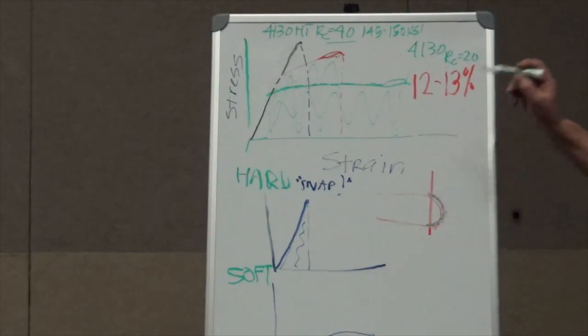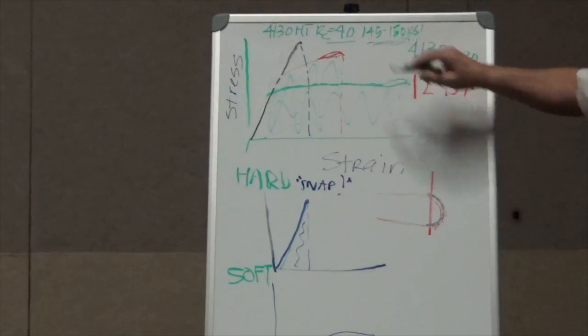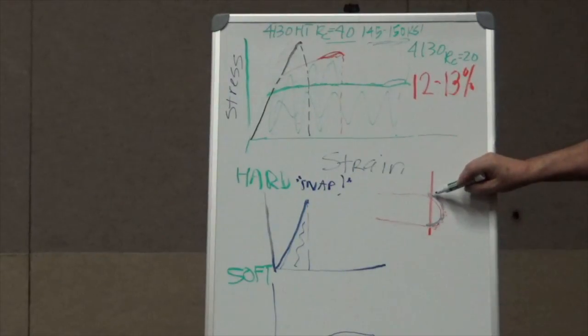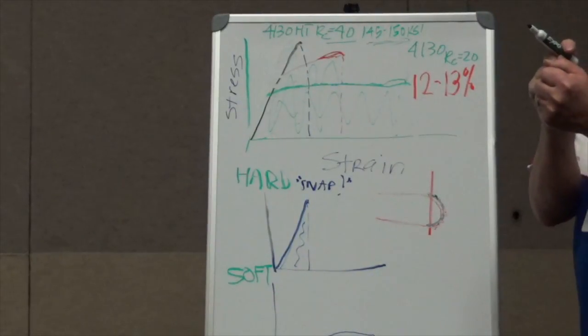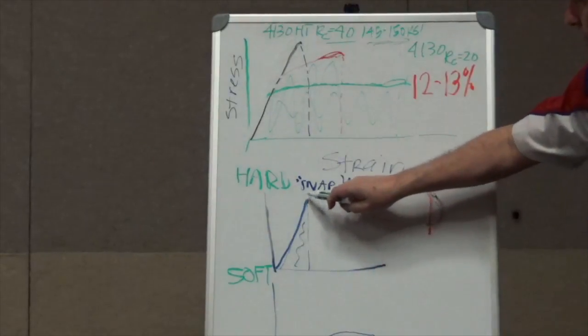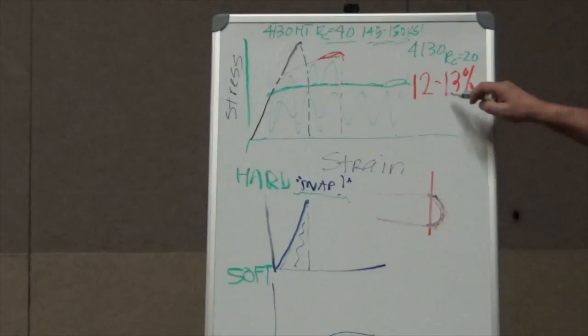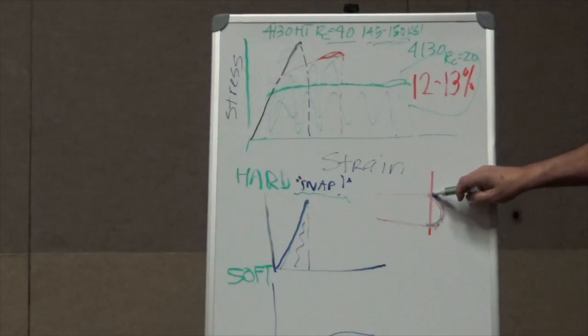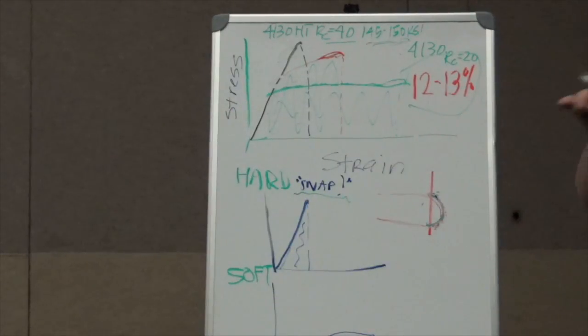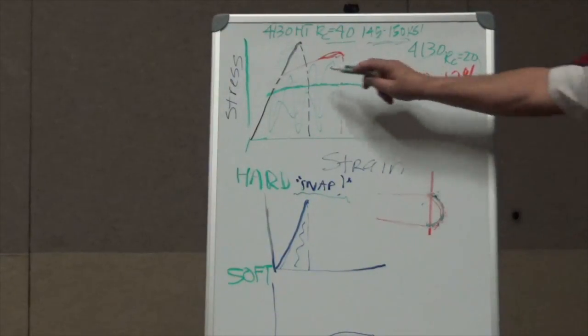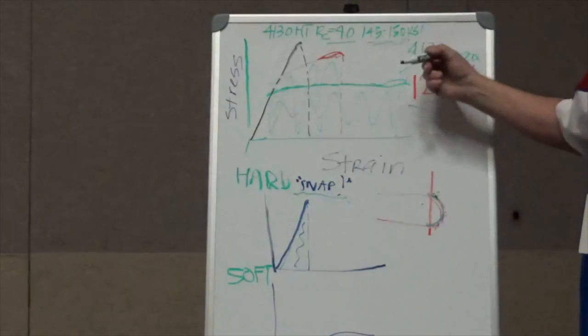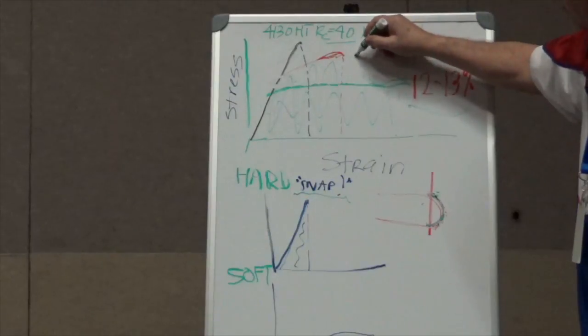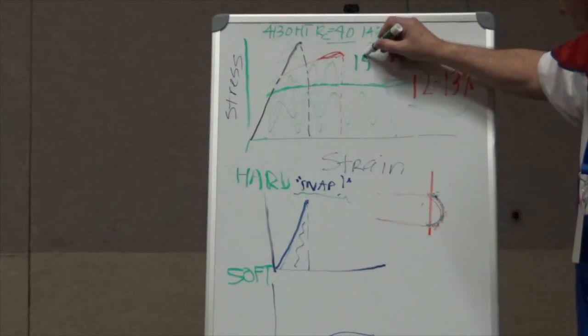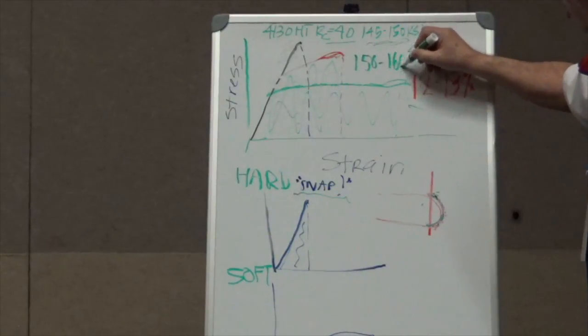So if the tube is really hard, though, this is the secret. When the tubes have the bigger numbers, whenever you find the first stress strain point, it will hold on, hold on, hold on, and snap. Just like that. What you want is this number, so that it will move around the tube and, at a micro level, disperse those stresses over and over and over. And what we found in our test was that the materials that were the better alloys seemed to be materials that had values of between 150 to about 160 with the higher strength alloys.